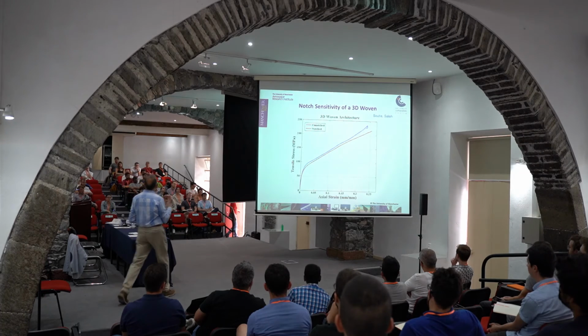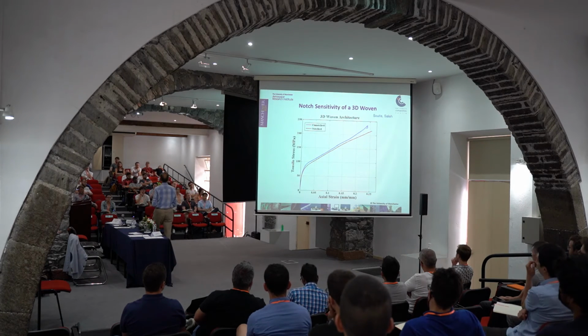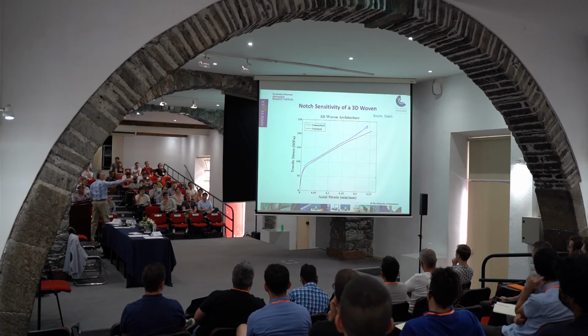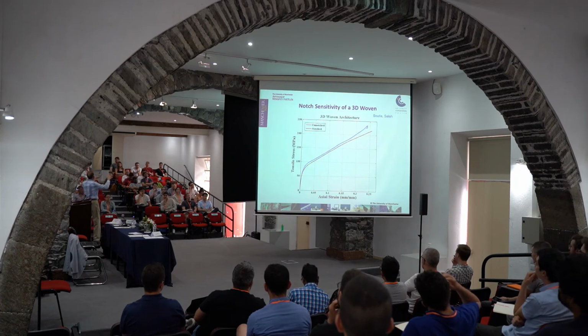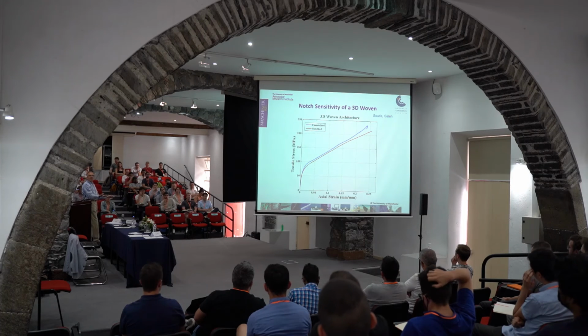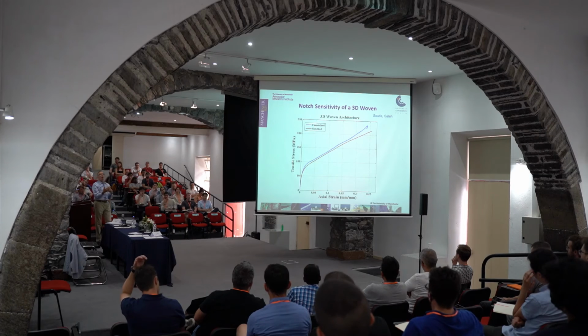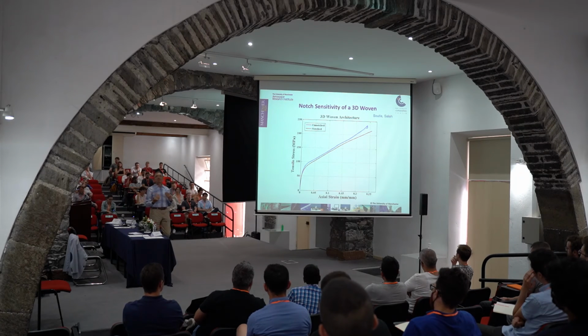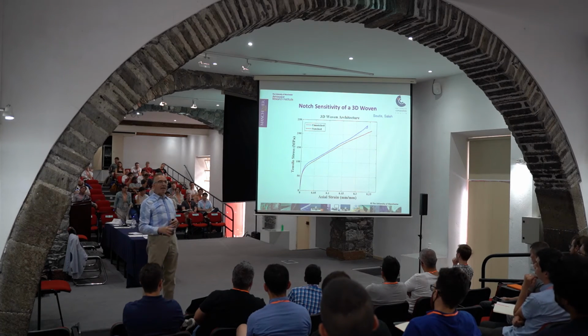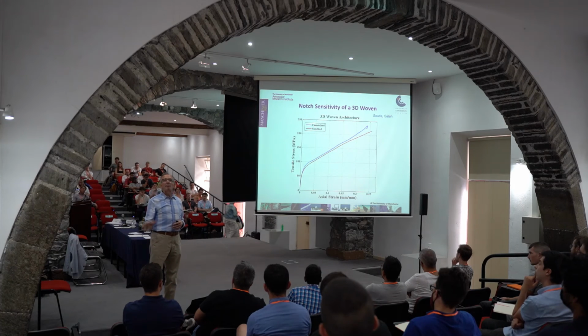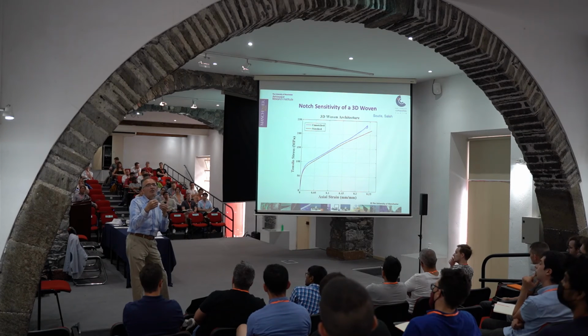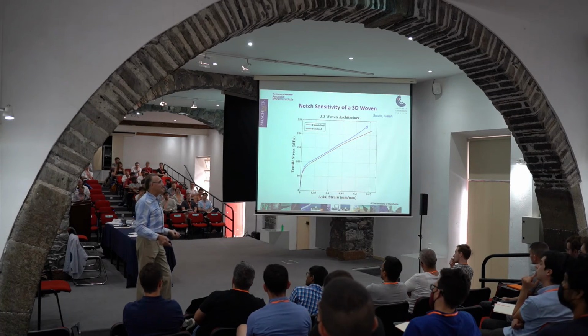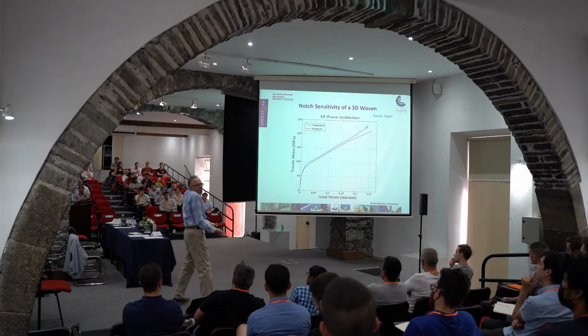And then when we look at the stress strain displacement, we can see actually that this stress response of the plane with an open hole is very similar to the one without the hole. And this is what we talked about earlier, the notch insensitive structure. You remove material and it doesn't feel the pain. So your laminate can support the load in the presence of a big hole. And this is because you have designed your three-dimensional fiber architecture where at the edge of the hole you don't have the stress concentration factor of 3, but you have the stress concentration factor of 1. You have no stress concentration.